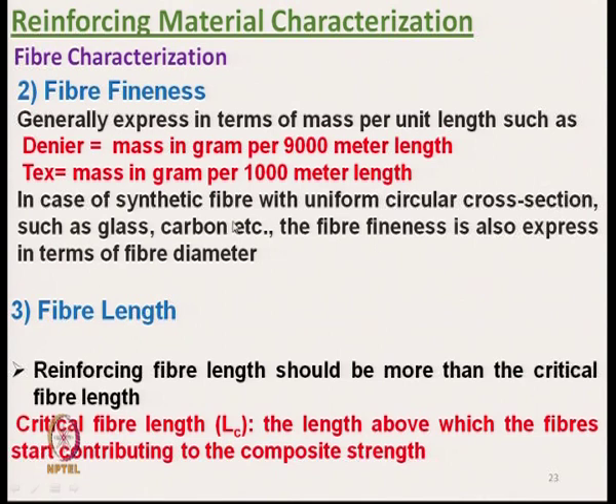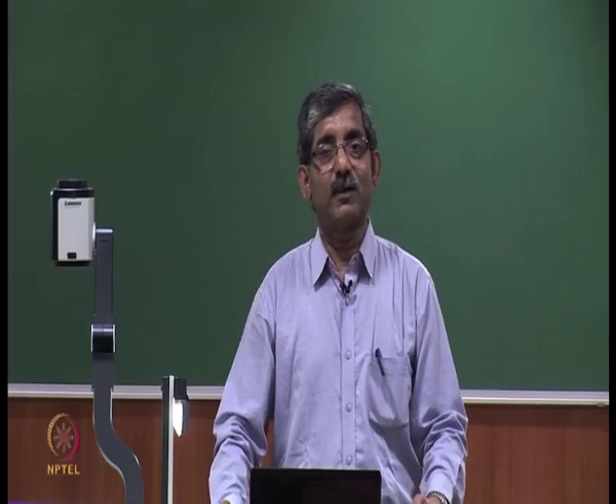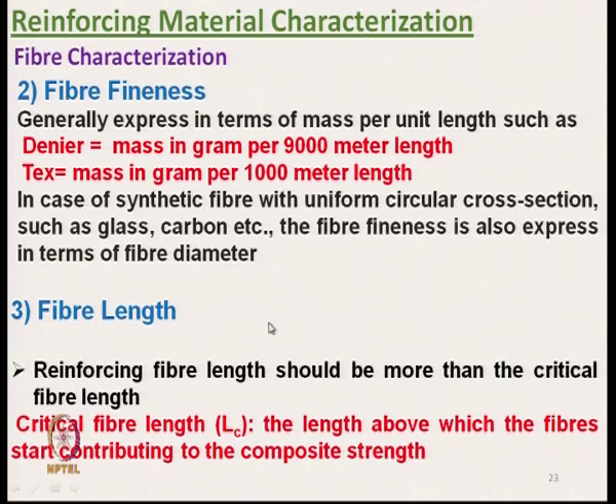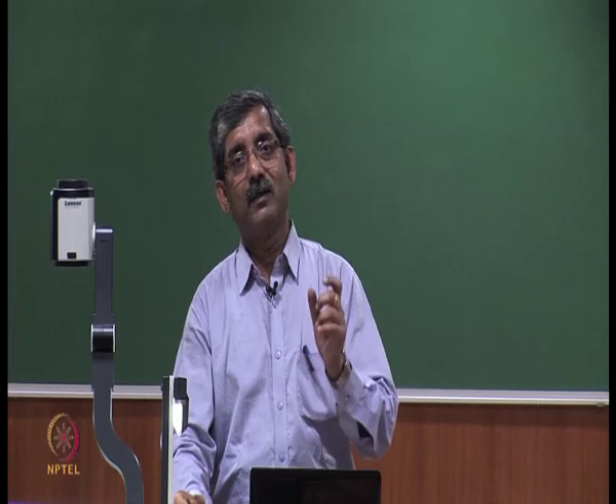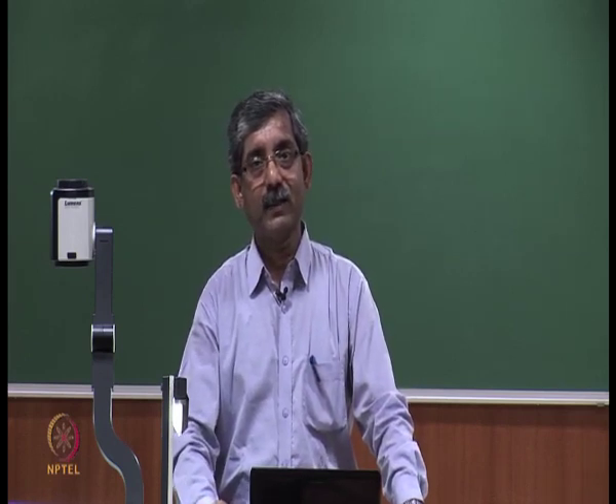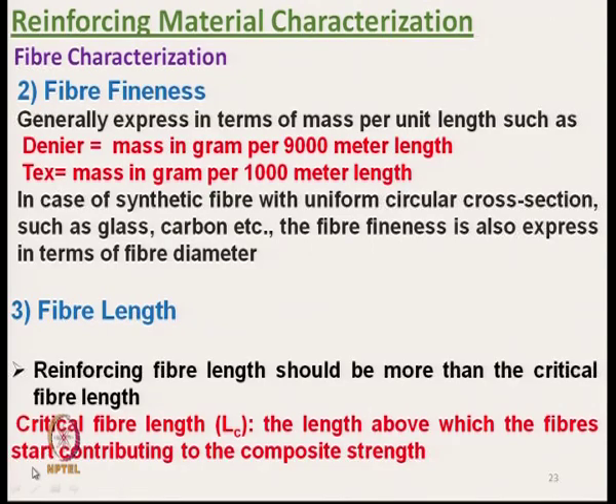In case of synthetic fiber with uniform cross section like glass fiber or carbon fiber, the fiber fineness can be expressed in terms of diameter or micron. Fiber length measurement is a very important characteristic for reinforcing material. The reinforcing fiber length should be more than the critical length of the fiber, that's very important. We can calculate the critical length of a fiber and accordingly decide the length of the fiber. The critical length is the length above which the fibers start contributing to the composite strength.